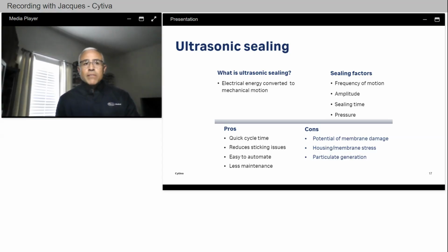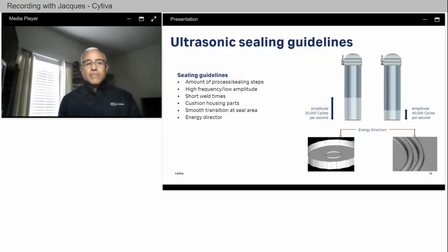However, you should be aware of certain challenges that may be encountered when using an ultrasonic welding method. These include the potential for membrane damage due to the vibration, high stress on the membrane and/or the housing, and particulate generation from these components. So the following general guidelines apply. Experience suggests that reducing the amount of process steps minimizes the risk of damaging the membrane during the welding. So use as few process steps as possible.